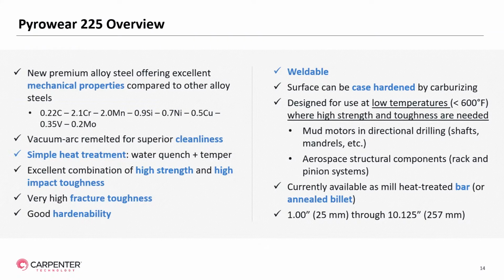This alloy is a premium alloy steel, and it offers excellent mechanical properties compared to other alloy steels. It has a relatively lean chemistry, as you can see, only about 0.22% carbon, a little over 2% chrome, 2% manganese, a little less than 1% silicon with about 0.7 nickel and 0.5% copper. We also add a little bit of the strong carbide forming elements of vanadium and molybdenum to this grade. It is vacuum arc remelted to give us superior cleanliness.